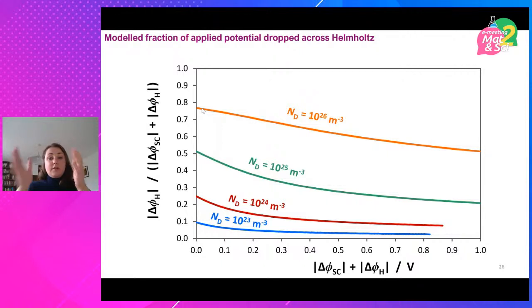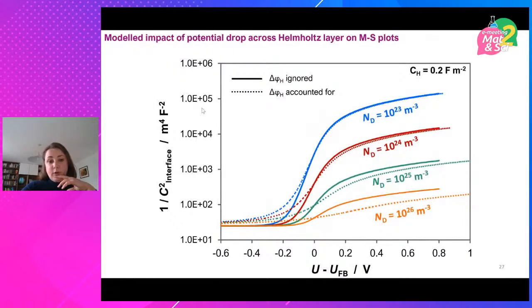And so, of course, this causes a total modification of how the Mott-Schottky values are aligned with the applied potential values. So the gradients become completely unrealistic. And so the way this modifies the plots, you can compare what the Mott-Schottky plots look like if you ignore the potential drop across the Helmholtz layer and when you take it into account. And you can see that for low doping levels, it doesn't matter too much. So that's the blue curve. But for high doping levels, that's the orange curve, the plots look completely different.